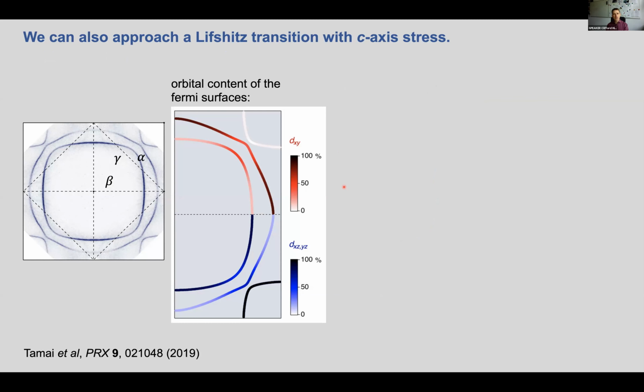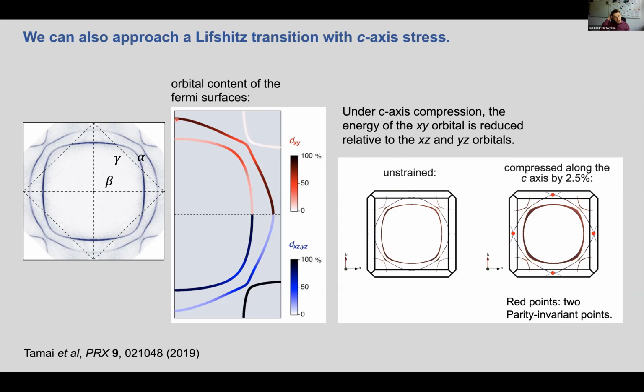So we can also approach this Lifshitz transition through c-axis stress. So I'll show here the orbital content of our Fermi surfaces. This gamma sheet is mostly composed of xy orbitals. It has a very strong xy character. Now, as we apply stress along the c-axis, we are restricting the space for the xz and the yz orbitals and increasing the space for the xy orbital. So this reduces the energy of the xy orbital.